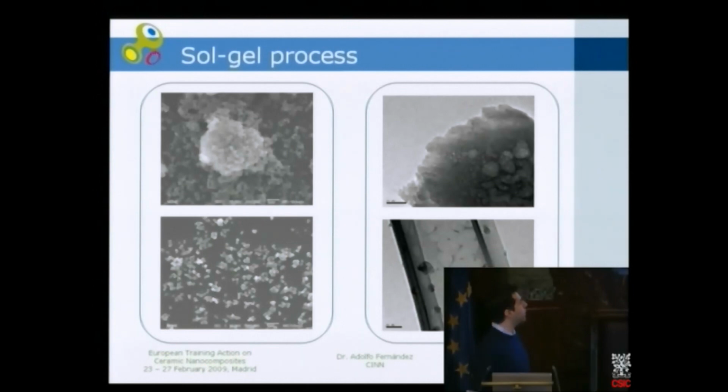If you prepare a stable suspension of nanoparticles, and this suspension is directly sprayed over liquid nitrogen and after that it is lyophilized, you are going to obtain non-agglomerated particles in comparison with normal heating drying methods.